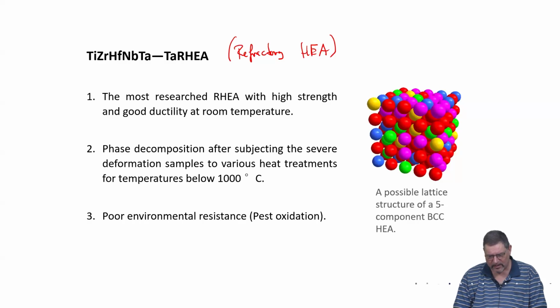And as far as we know, it is also available as a single phase high entropy system. So it means one common lattice structure and elements are distributed over the lattice sites at random. Obviously, whenever you treat the material so that either kinetics are enhanced at some temperature, or if you wait long enough at lower temperatures, the material will be showing tendencies for destabilization of the single phase solid solution, and we have discussed why this is. So in this case, if temperature treatment is done at temperatures less than 1000 degrees centigrade, so quite at a high temperature already, then the chances are very high that for the compositions one typically chooses, second phases precipitate and form.